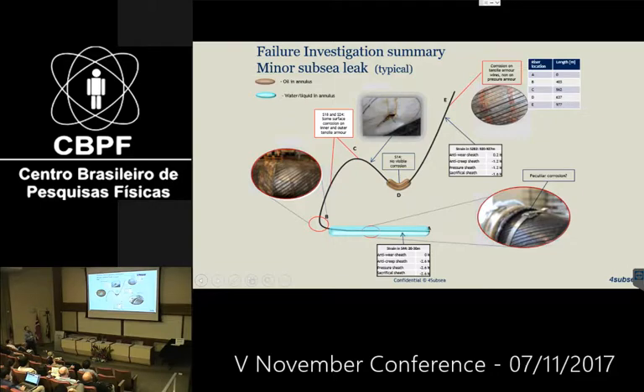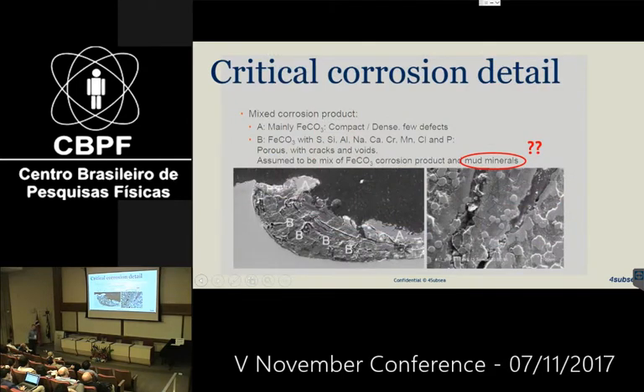As a typical case, we found some peculiar corrosion down here. And then we need to go and discuss with people. Very often we have been consulting with IFE in the last years, and these are examples of an investigation that was done together with IFE. That was this strange corrosion spot. In some areas we find a compact iron carbonate film, which has few defects and gives adequate protection. But then we find an area where there is a porous film, which is not giving you the protection you need, so that you could have aggressive corrosion underneath it and around it.